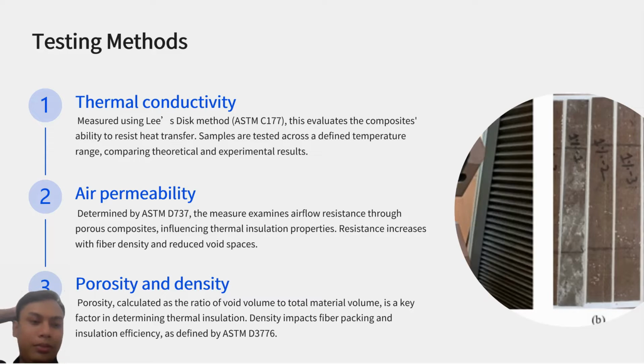Air permeability determined by ASTM D737. The measure examination airflow resistance through porous composite, influencing thermal insulation properties. Resistance increases with fiber density and reduced void space. And three, we have to test porosity and density. A porosity calculated as the ratio of void volume to total material volume is a key factor in determining thermal insulation. Density impacts fiber packing and insulation efficiency as defined by ASTM D3776.